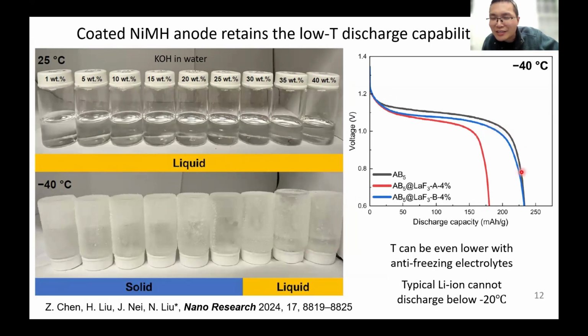The black one is the pristine uncoated AB5. If we coat them properly, you can deliver the same capacity at -40 C. So the coating actually didn't make the performance worse, and it prevented the dissolution. That's very good. But if you use a different type of coating, then you can indeed make the capacity lower at low temperature. Okay, so -40 is a very extreme temperature, because typical lithium ion cannot discharge below -20 C. So this is a big success for nickel metal hydride.